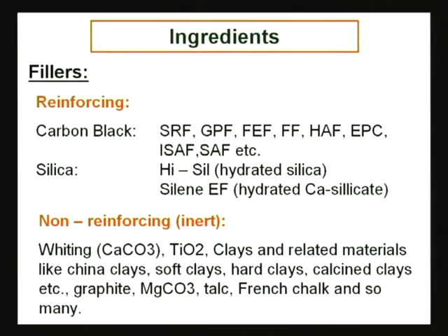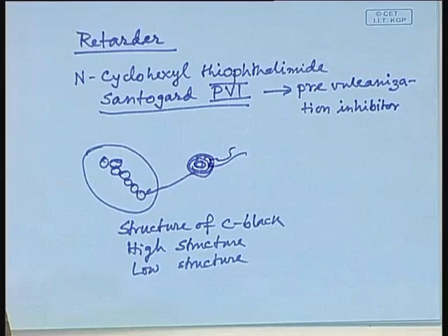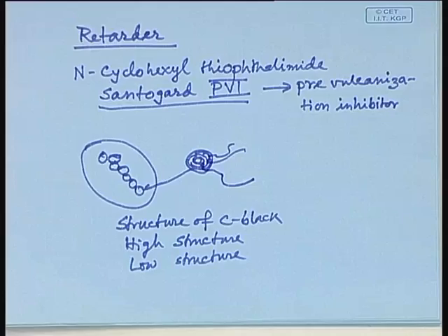So, this is carbon black, and by virtue of that floppy structure, by virtue of those free volumes, the ends of the rubber molecules and the segments of the rubber molecules get occluded within the porous structure. You see, here is some free volume, free space. Now, a part of the rubber molecular chain, say some segment, can be occluded over there, can be entangled over there. Not only that, ends of the polymer chain can be anchored over there. So, this kind of anchorage through occlusion of part of the segments or ends of the polymer chains will occur in our carbon rubber particle, and here is the mechanism of reinforcement.